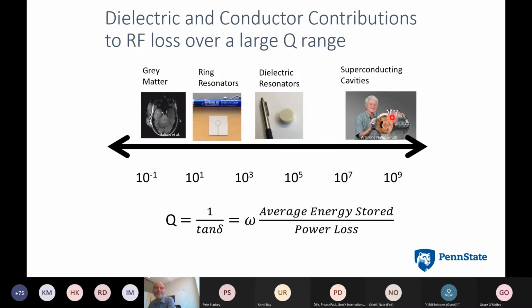Here we have a conductor and an insulator, and the insulator is basically vacuum in this case, very, very low loss, and the superconducting walls have very, very low resistivity, super high conductivity. So you can see here, at least for this construction, we have Q values of 1 billion, right? Incredibly high Q values because this structure is very, very low loss. I think the operating frequency is around 500 megahertz.